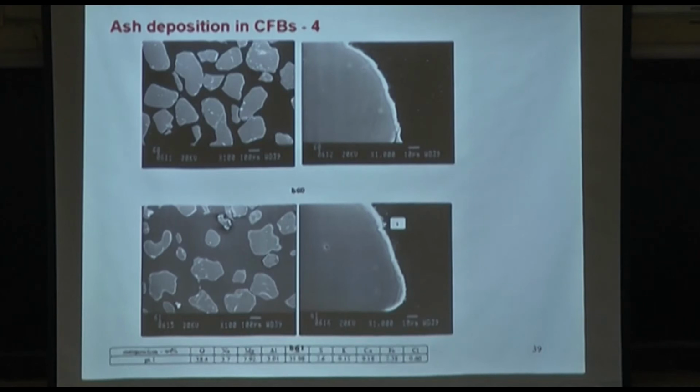Okay. So you have a fine particle, and a large particle. You are giving both of them the same velocity, so which will elutriate first? The fine one, right? But the fine ones have larger specific surface area. So it will actually provide more surface to the sticky minerals coming out from the matrix of the coal. And the finer particles can get access to the sticky compounds much faster than the larger ones.